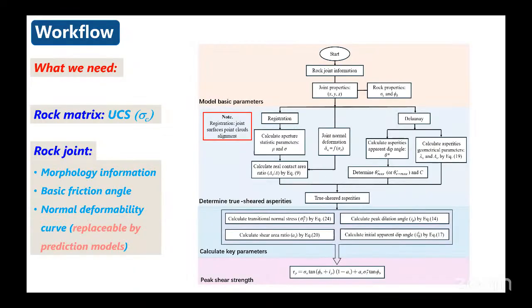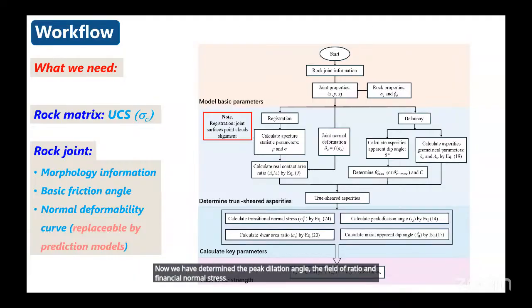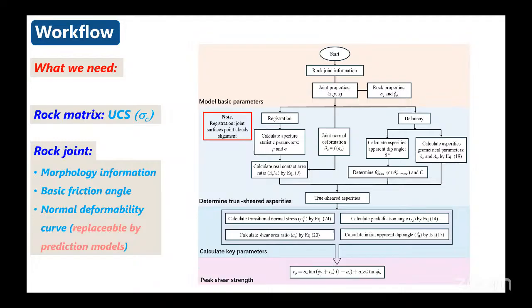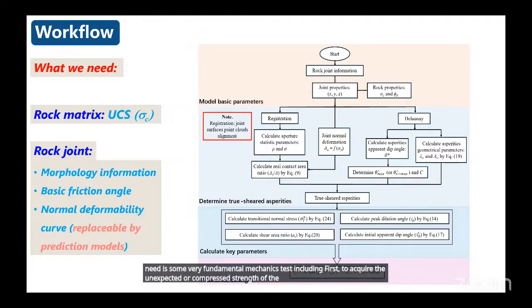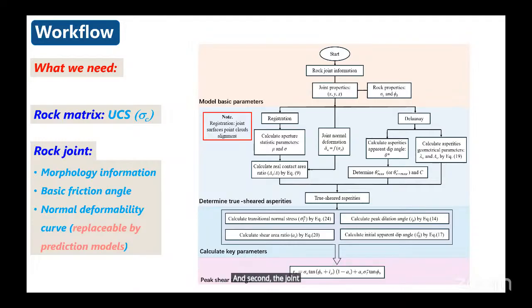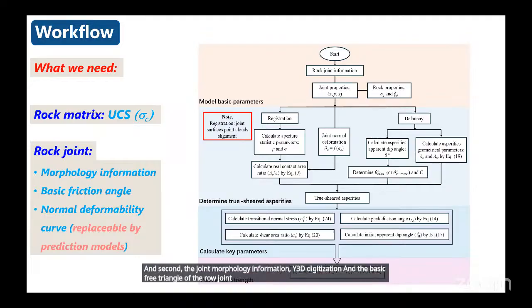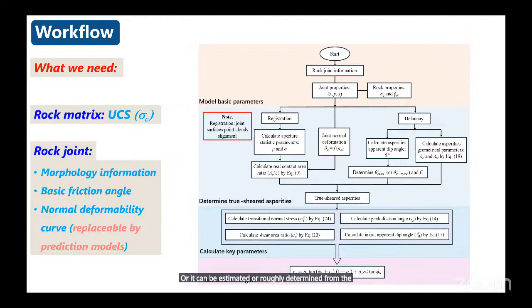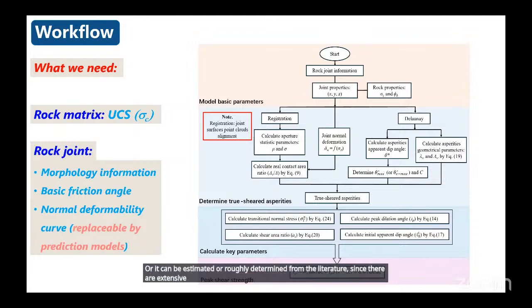Now we have determined the peak dilation angle, the shear area ratio, and the transitional normal stress. And thus, the peak shear strength can be predicted. To implement this, what we need is some very fundamental rock mechanics tests, including, first, the uniaxial compressive strength of the rock matrix. And second, the joint morphology information via 3D digitization, and the basic friction angle of the rock joint. This value can be measured by a direct shear test on flat rock joints, or it can be estimated or roughly determined from the literature, since there are extensive data on the basic friction angle.